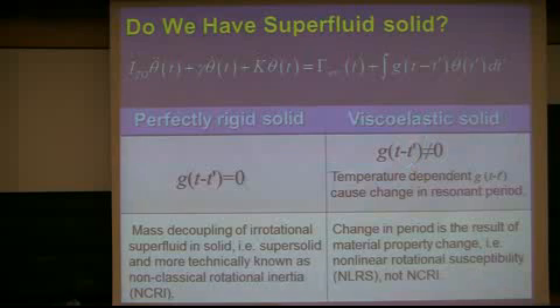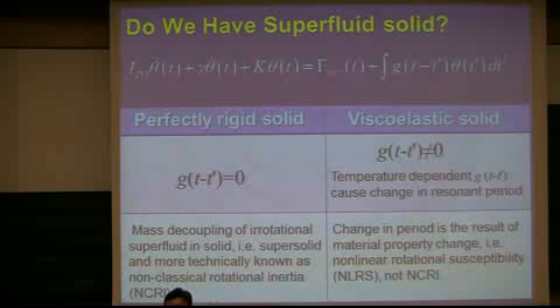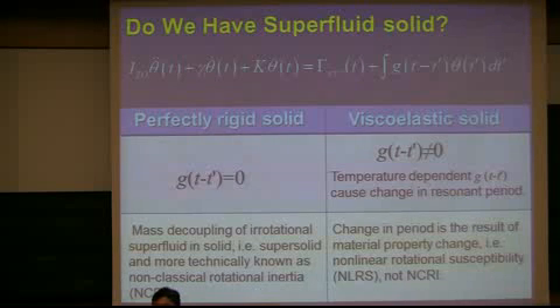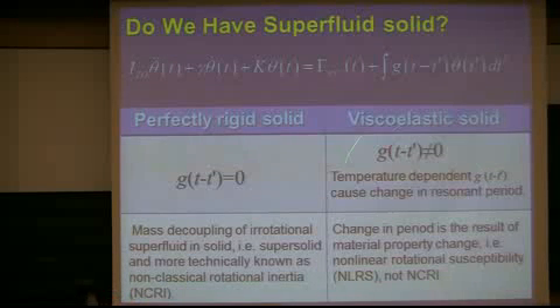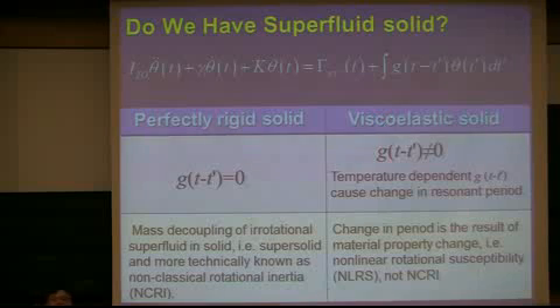So think about it. If you have a viscoelastic solid and you shake it back and forth, then inside the solid helium there is a stress built up. Because of that stress, you could have a change in the resonant period as well. And especially if this back action term, which is directly proportional to the elastic property of solid helium, is temperature dependent, then the reduction in the resonant period can be explained by this viscoelastic solid scenario.